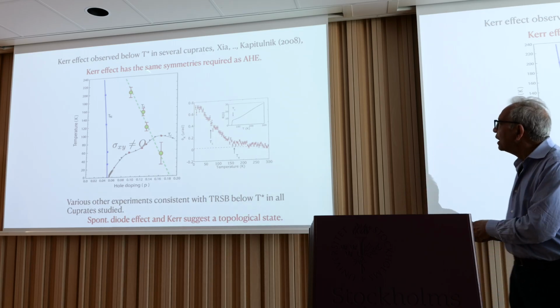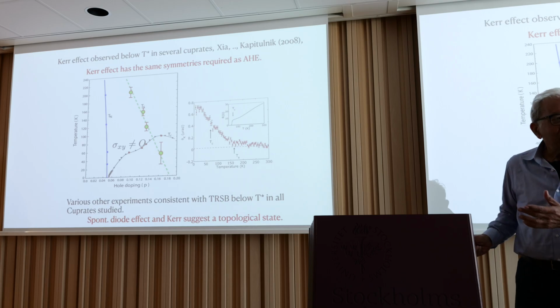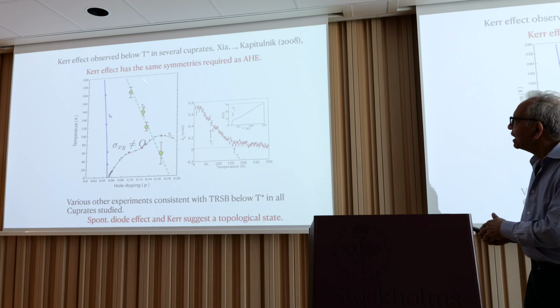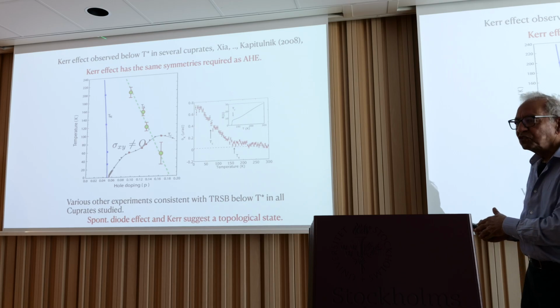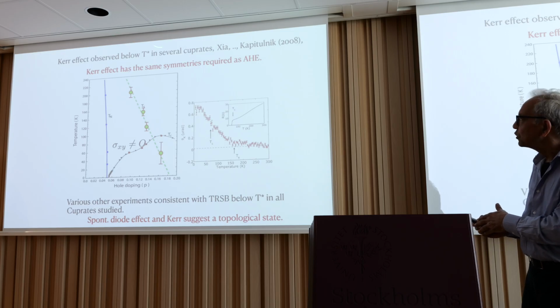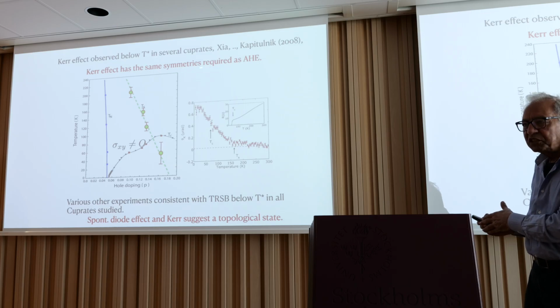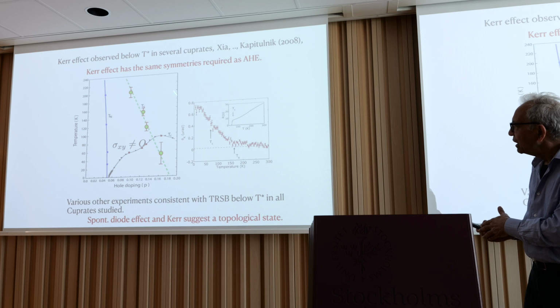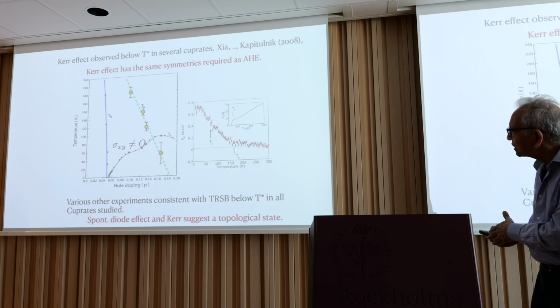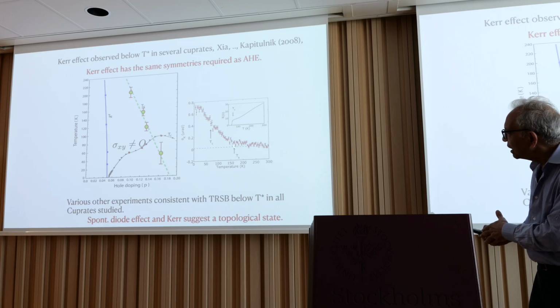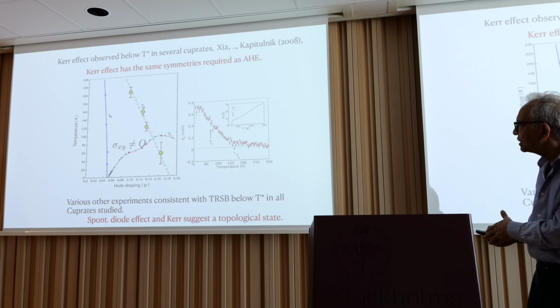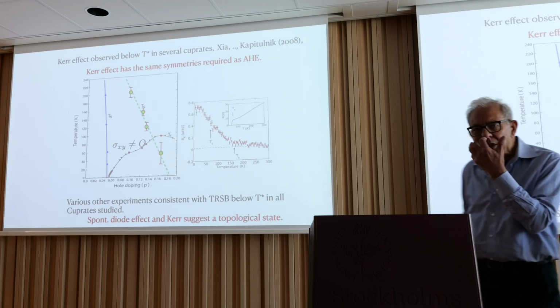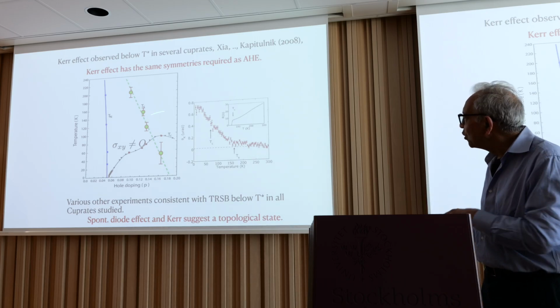Now, in this compound, unlike rhombohedral graphene, a DC anomalous Hall effect is not seen. However, and that's related to the curse that I mentioned, Kerr effect is observed in 4 different families of cuprates. Now, Kerr effect has the same symmetries required as the anomalous Hall effect. And here is Aharon Kapitulnik and friends' Kerr effect setting in at a specific temperature. And this temperature happens to be the pseudo-gap temperature for that doping.